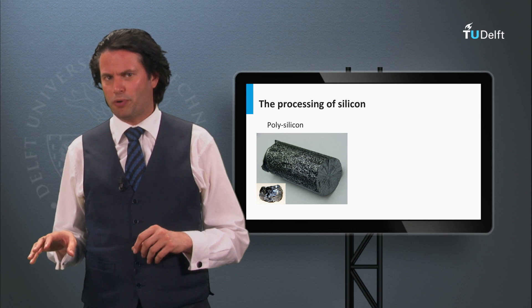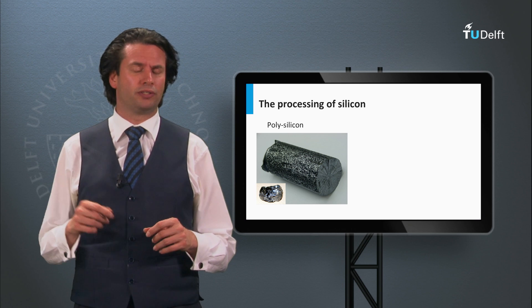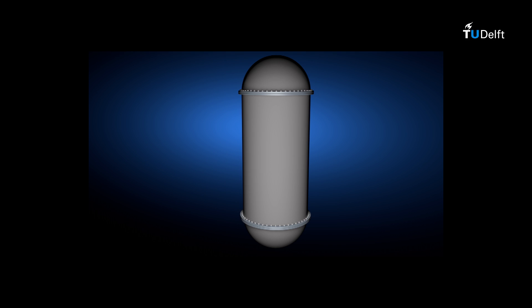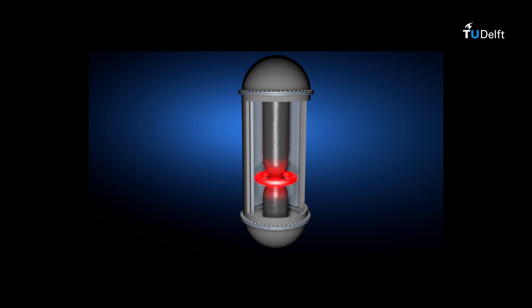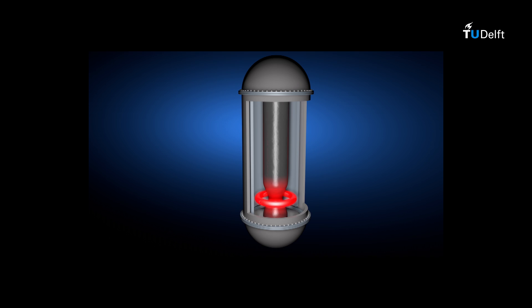The second method to make monocrystalline silicon is the float zone process, which results in monocrystalline silicon ingots with extremely low densities of impurities like oxygen and carbon. The source material is a polycrystalline rod from the Siemens process. The end of the rod is heated and melted using a radiofrequency heating coil, and the melted part is put in contact with a seed crystal, where it solidifies and adopts the seed crystal's orientation — either 1-0-0 or 1-1-1. As the molten zone is moved along the polysilicon rod, the single crystal ingot grows, and many impurities remain in and move along with the molten zone.